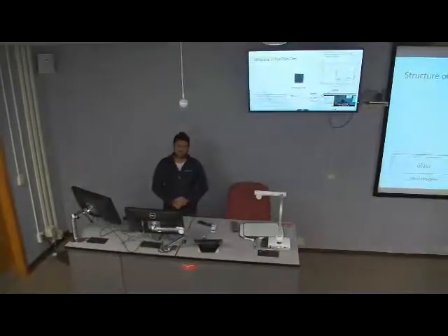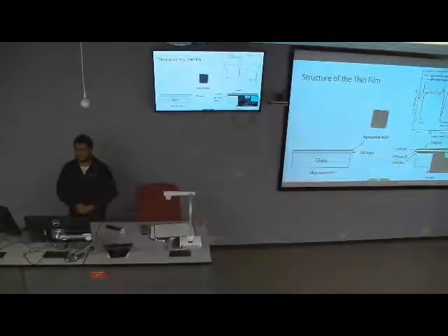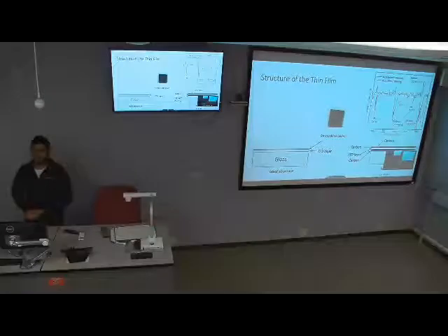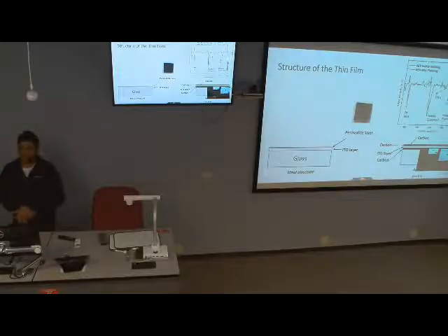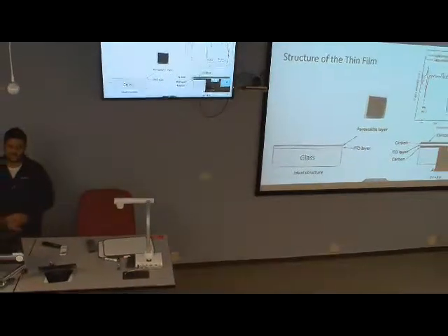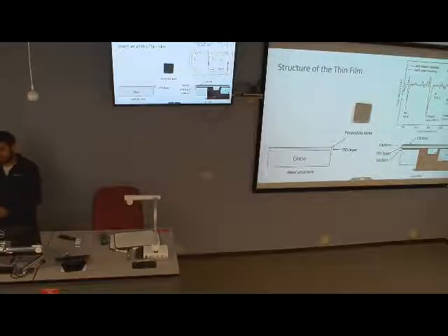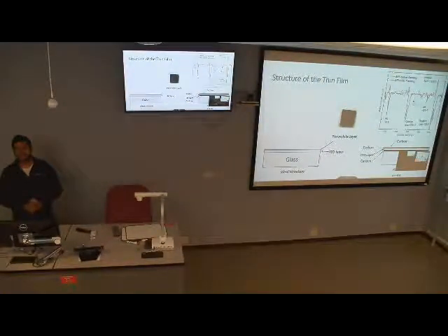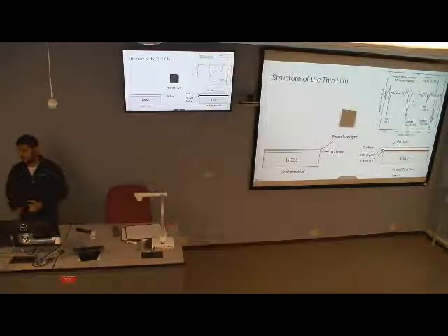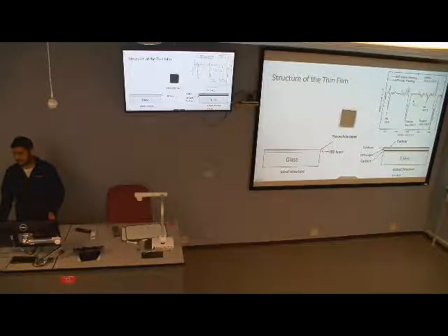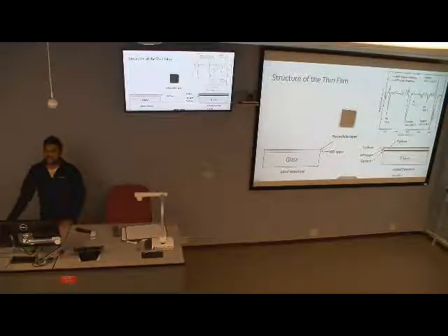So we synthesized the perovskite structures, and we characterized those structures using standard techniques like UV-visible absorption spectroscopy, scanning electron microscopy, and X-ray diffraction. After characterizing those samples, we put them inside an ultra-high vacuum chamber, and we studied the thermal stability and the adsorption kinetics at ultra-high vacuum conditions. There we characterized the elemental composition of the sample using Auger electron spectroscopy.